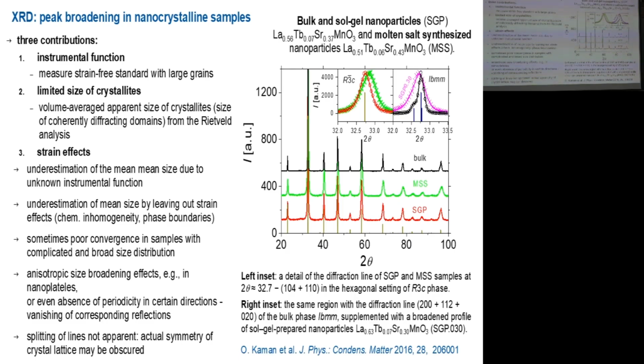For example, in this figure, you can see 3 or 4 diffraction patterns of some perovskite phases. Again, it's quite complex perovskite, this lanthanum strontium doped with terbium. And there are different samples prepared by 2 different methods, nanoparticles prepared by 2 different methods. There is also a nice bulk sample with large grains, well crystalline, and in this inset there is even a 4th sample of slightly different composition. And like looking at these tiny regions of this most intense diffraction line, you can see that the situation is quite complex.